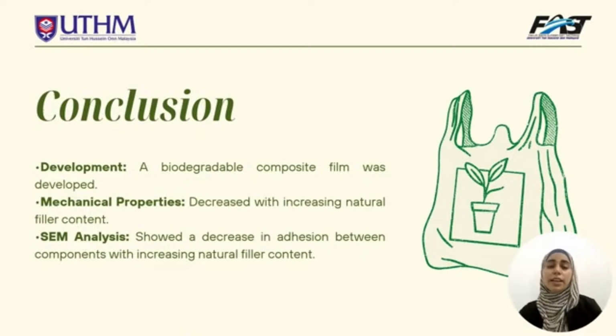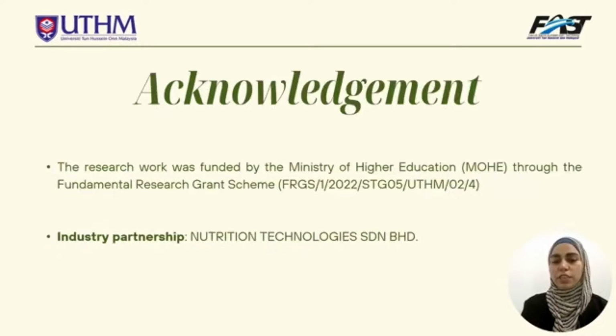In conclusion, I was successful in making a biodegradable composite film, and through characterization, I came to know that all the mechanical properties decreased with increasing natural filler content, and the SEM analysis also showed a decrease in adhesion between the components with increasing natural filler content.